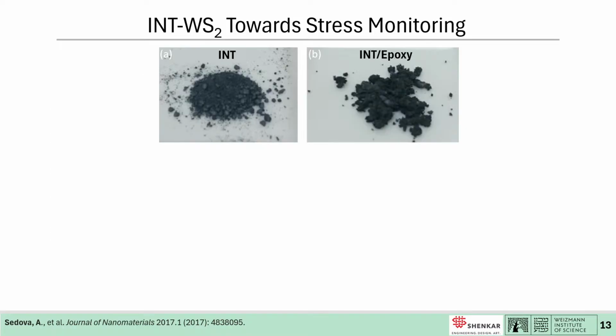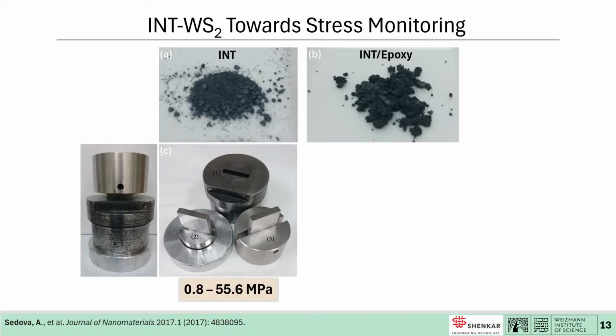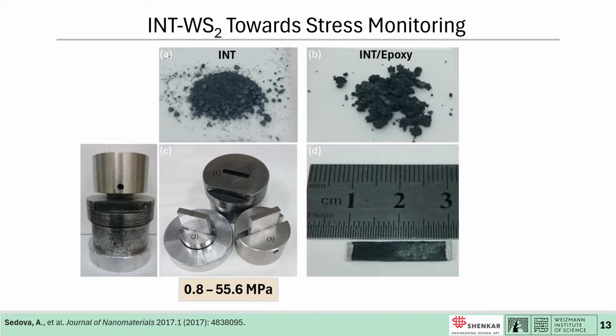So we changed our approach, and we said we will use the polymer as a binding agent and not a dispersing medium. We needed to design a device for the sample preparation where we could prepare samples under different loads. And eventually we obtained those samples. We dried them, annealed them, and that way you harden the polymer and obtain a hard sample. We could achieve samples, which I think is a great achievement, as we know that the electrical resistance will increase with the size of the sample.